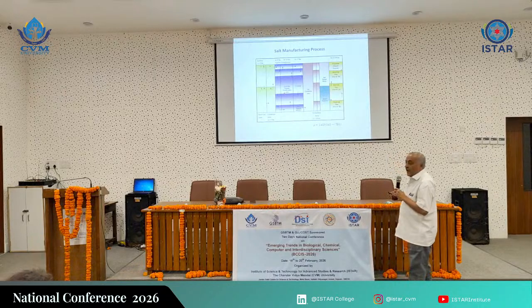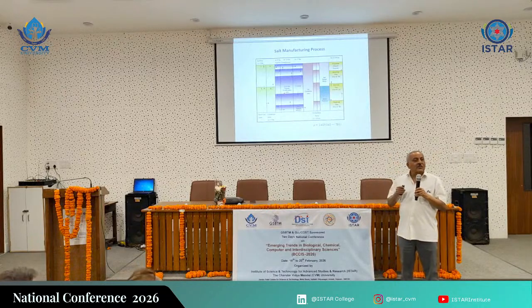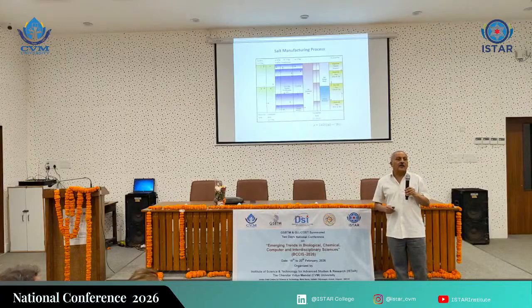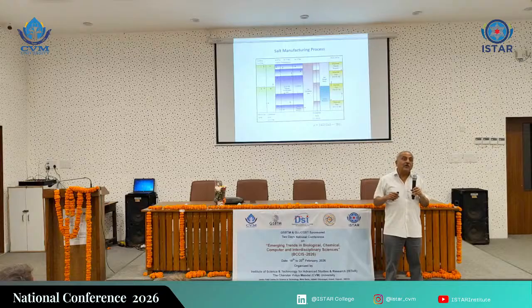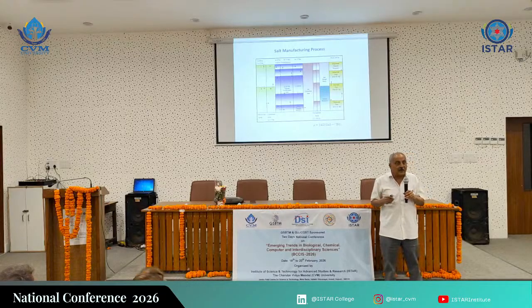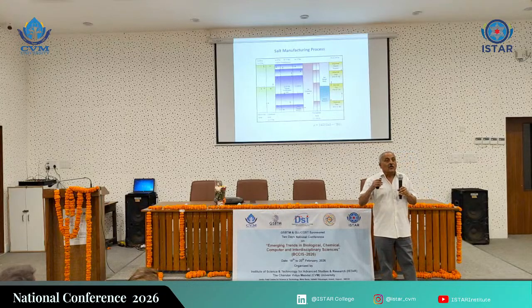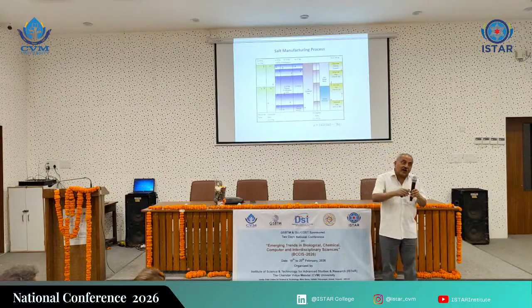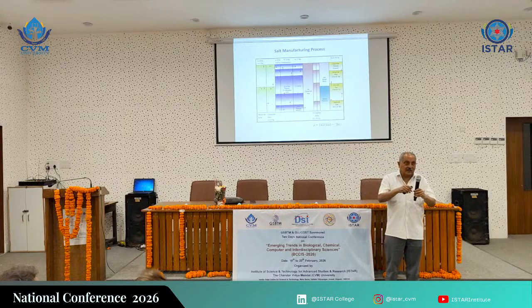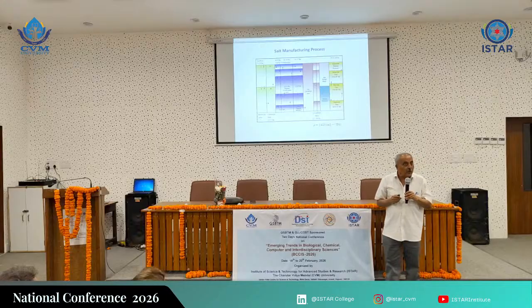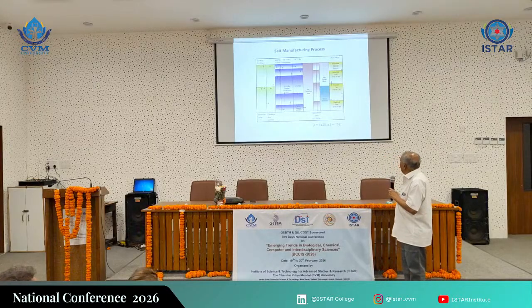So, at 29% concentration, the mother liquor is discharged from the crystallizer. Why? Because by that time magnesium sulfate has come to saturation, and it also starts to co-crystallize with the salt, and the salt becomes impure. And this is called bittern.